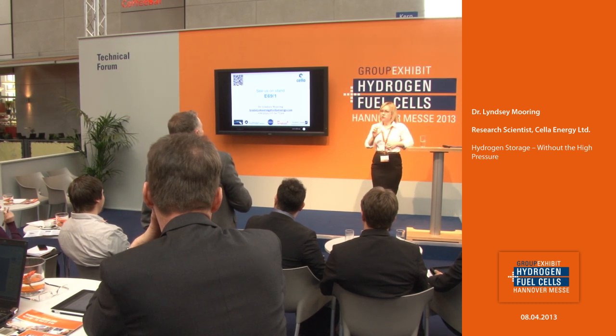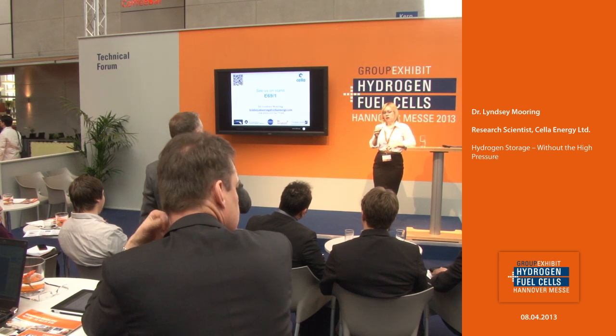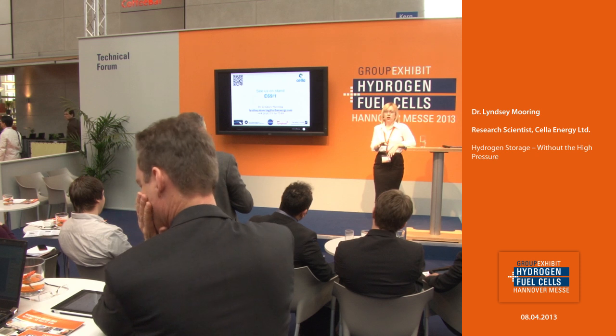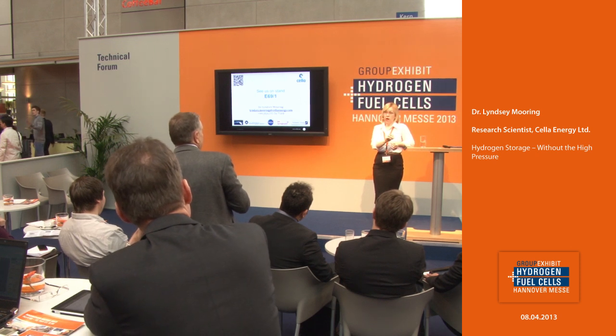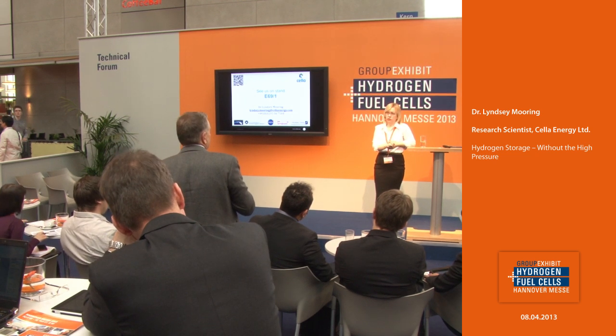We're trying to tune it so that we can tweak the hydrogen release depending on the application. For the transport fuel at the moment, we're trying to hit that from each individual pellet you would get the hydrogen released within, let's say, a 3-minute window. Because if we can tailor the hydrogen release specifically, then we can design the hydrogen buffer volume to be the minimum that it needs to be safe. So that, let's say you turn your car off and it's set off the last pellet, you then have a buffer volume to deal with. So we're trying to look at the size of the pellets to see what is the best geometry, and also to look at the hydrogen content and the material we're blending it with to fully tailor that hydrogen release.